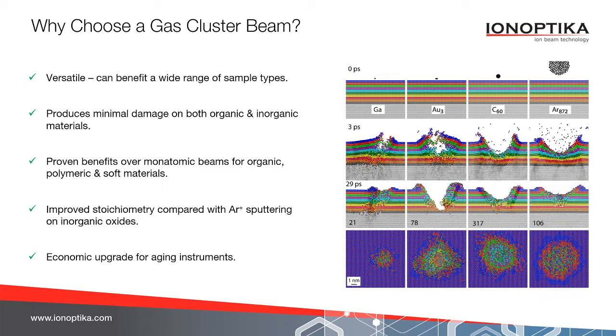As the size of the ion beam is increased, so as we go from gallium to gold to C60, which is obviously a collection of carbon atoms, to something like an argon cluster, the penetration depth reduces and the damage reduces also. The crater size increases, but the actual damage imparted into the sample is reducing in all cases. So an argon cluster beam does not break bonds in the materials that it hits. So that is why it's so useful.